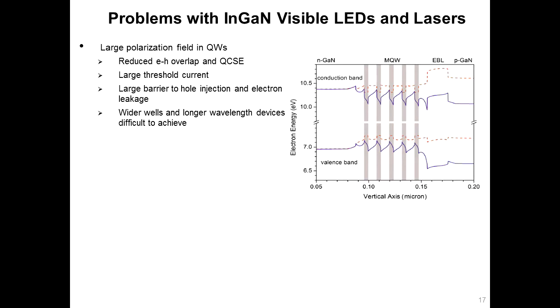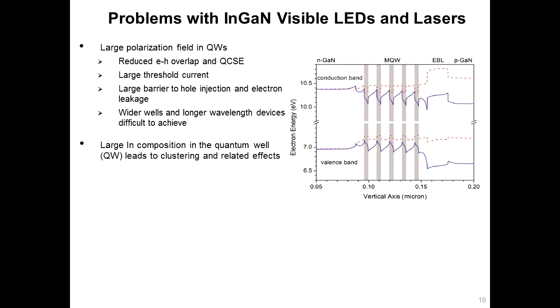So now, indium gallium nitride as an alloy is used to get different visible colors, all the way from violet to green and so on. Now, if you look at the band alignment of an LED, this is how it looks, and this is because of the polarization field. You have these peculiar barriers and notches, and this causes all kinds of problems. One is the reduced electron-hole overlap that I talked about. If you make a laser, it increases the threshold current. There's a large barrier to hole injection, and everybody knows that most of the holes pile up in the first 2 quantum wells or so. And the wider wells and longer wavelength devices are therefore difficult to achieve.